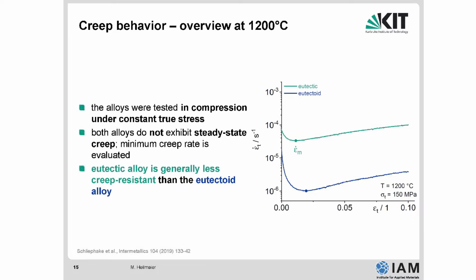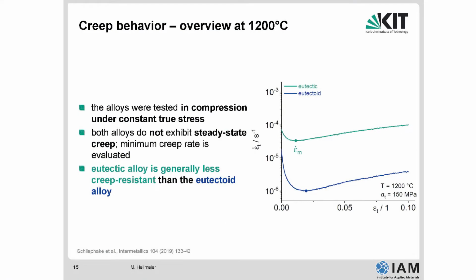What then you will see is that the creep rate of this eutectic alloy is much greater than the creep rate of the eutectoid alloy, which is not good news. You would like to have creep rates very much down here, meaning it would take a long time to see a creep strain of, say, 5%. Imagine a turbine blade in a rotating environment. This turbine blade starts elongating while you apply the rotational, the centrifugal load, right? So it cannot elongate infinitely because there's a casing which the blade will scratch on, right? When the turbine blade reaches the casing, it either breaks into parts or it scratches the casing. In any case, it needs to be replaced.